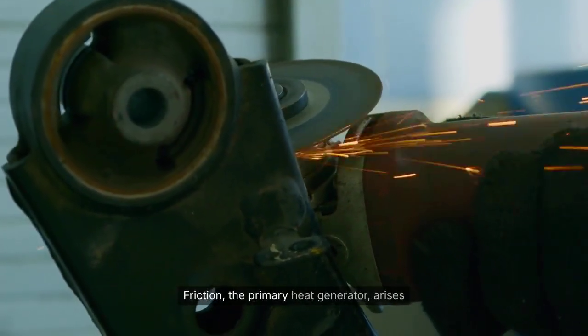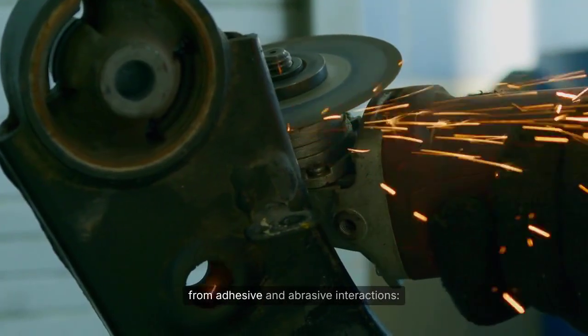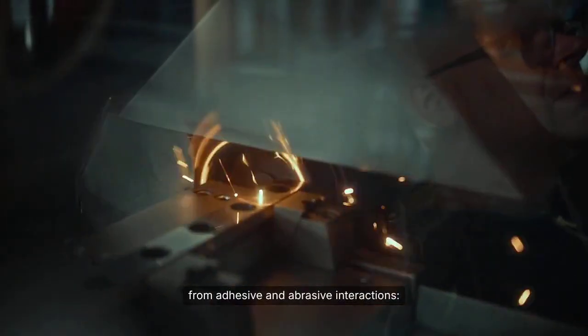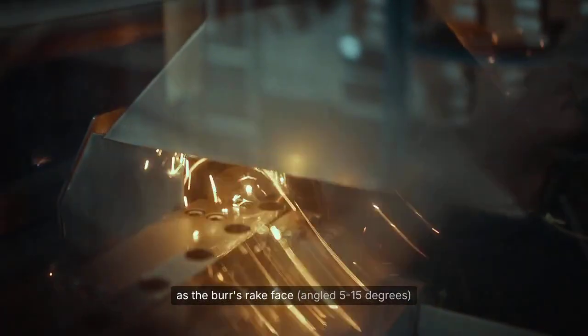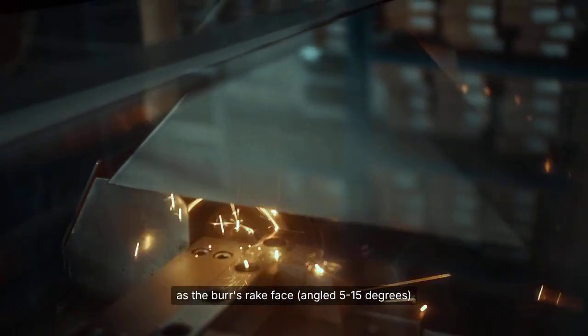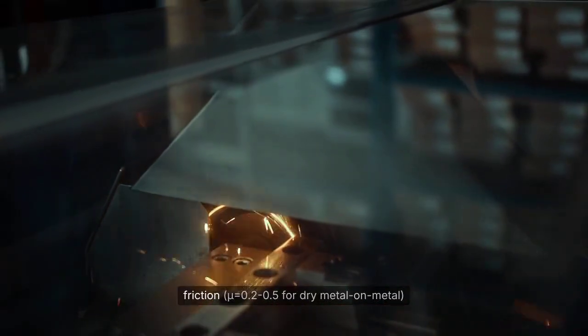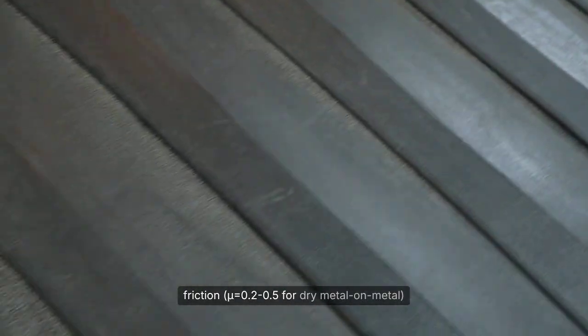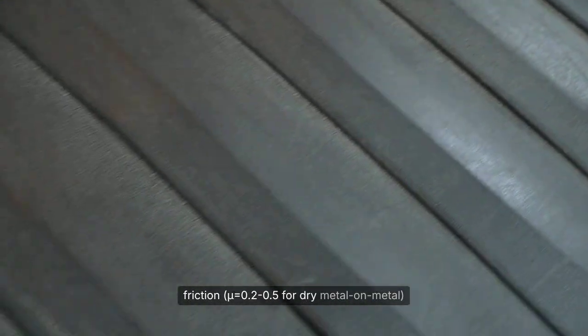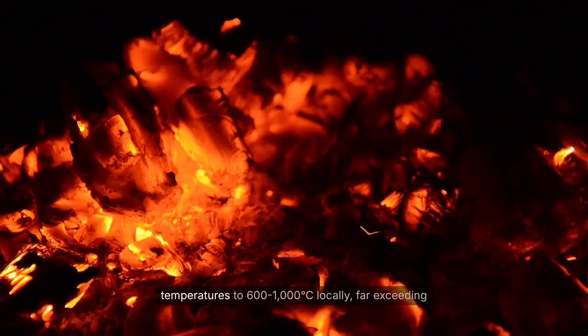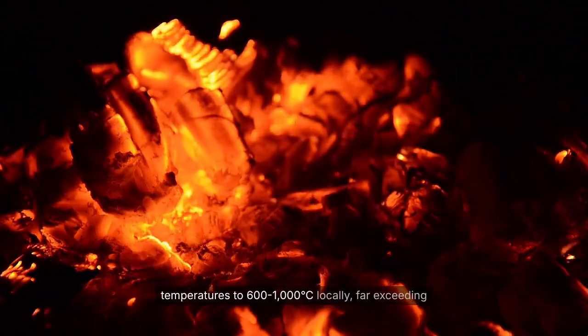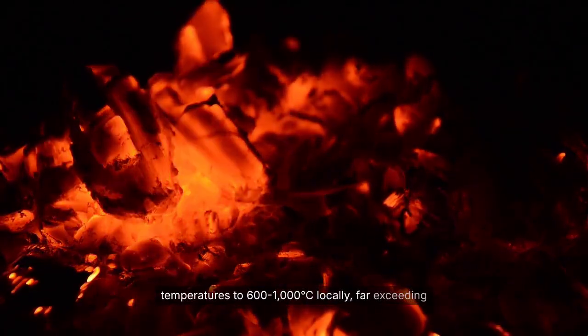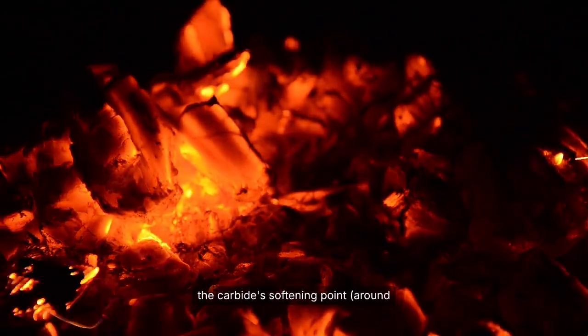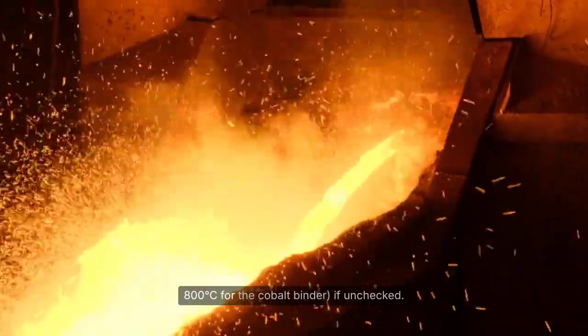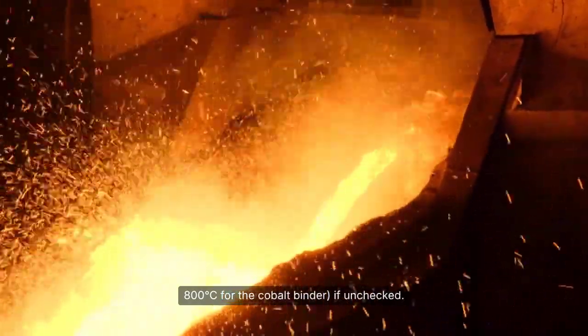Friction, the primary heat generator, arises from adhesive and abrasive interactions. As the burr's rake face, angled 5 to 15 degrees, slides against the workpiece, Coulomb friction, Mu equals 0.2 to 0.5 for dry metal on metal, produces tangential forces that elevate temperatures to 600 to 1,000 degrees Celsius locally, far exceeding the carbide's softening point, around 800 degrees Celsius for the cobalt binder, if unchecked.